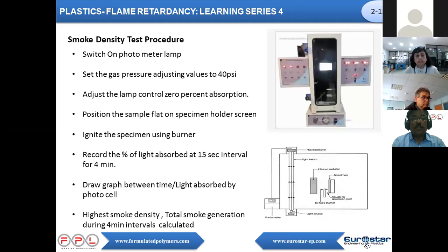Then the test procedure: first turn on the photocell lamp, switch on the gas, ignite the burner and set the pressure at 40 psi. Calibrate the photocell at zero absorption. Then ignite the specimen using the burner. The specimen should be ignited from the bottom. Observe the light absorption at 15 second intervals for a 4 minute duration. The test should be repeated with 3 sets of specimens. Maximum smoke density and total smoke generation can be calculated by drawing a slope between time and light absorption.